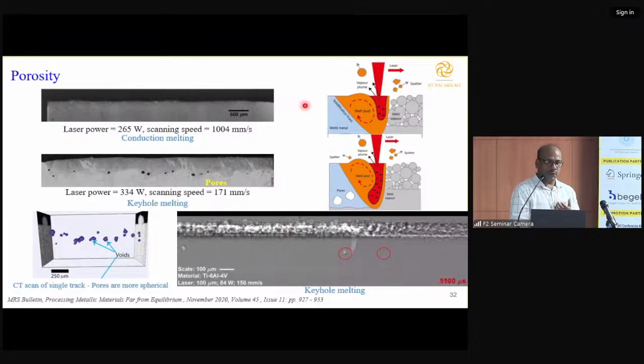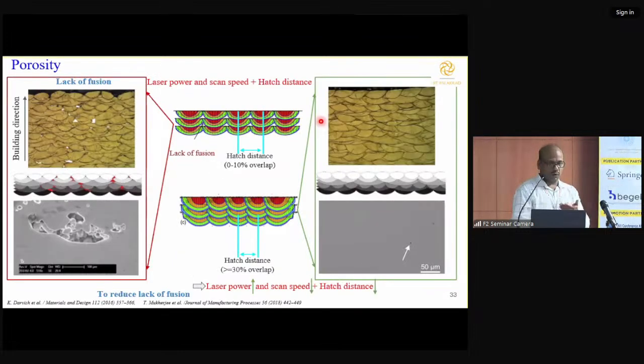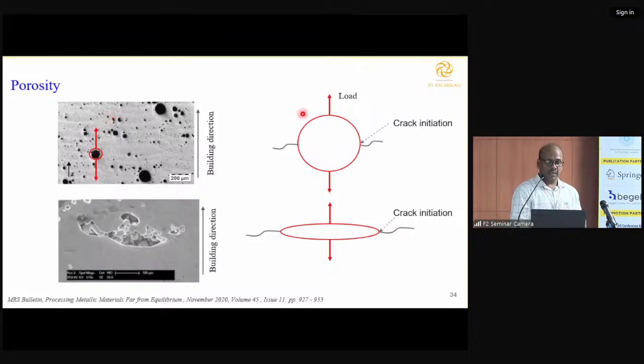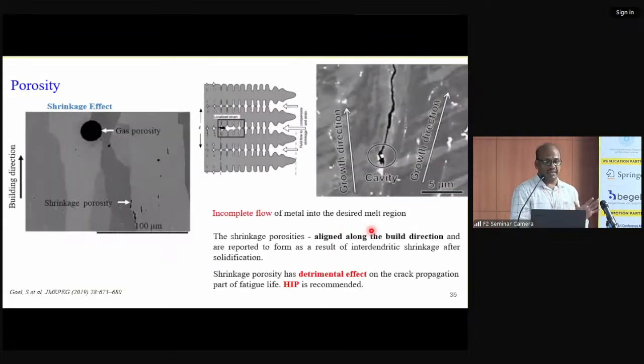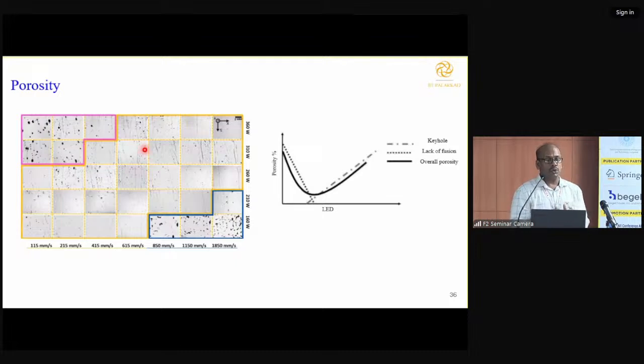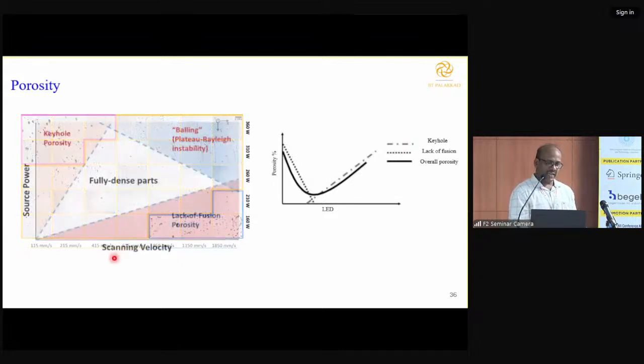So whenever you do optimization, apart from the geometrical optimization, we have to do optimization based on this porosity defect. I'll go further. Not only porosity, there is also lack of fusion. If you have pores, cracks initiate and the part fails very fast, so we should consider that also. Whenever solidification is happening, shrinkage effect also comes, and that also leads to pores, called shrinkage pores. Now this optimization should be done based on geometrical aspects as well as defect aspects. This is the area for a given scanning velocity and source power; this set of parameters will give a fully dense product. This is process mapping development. For any process you work on, you are supposed to do this process mapping development. That will give a lot of idea.